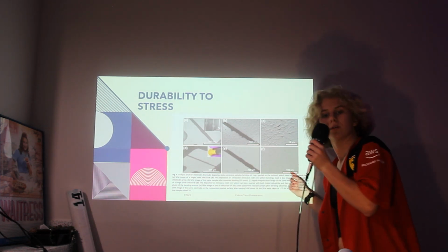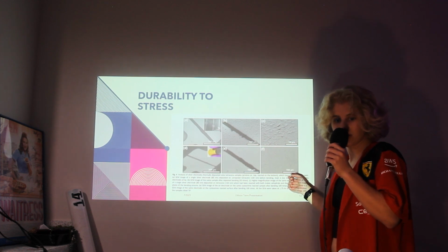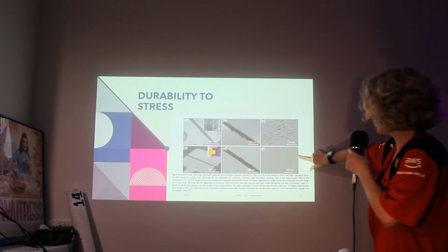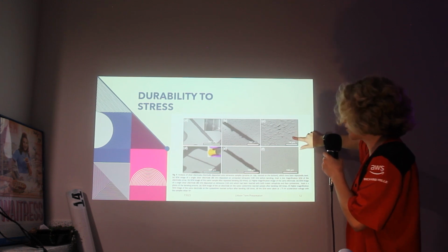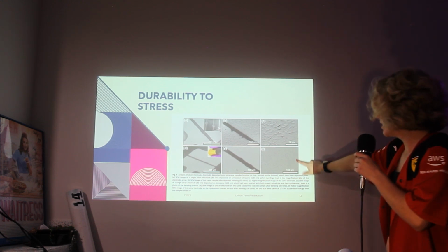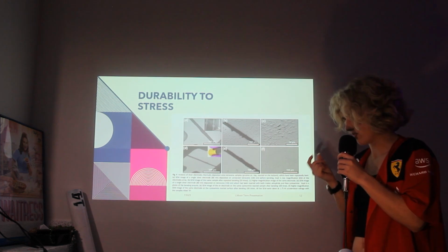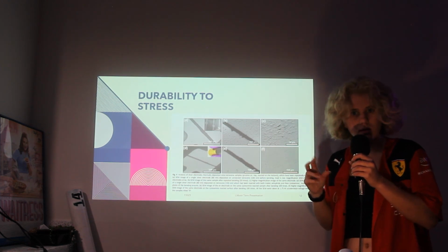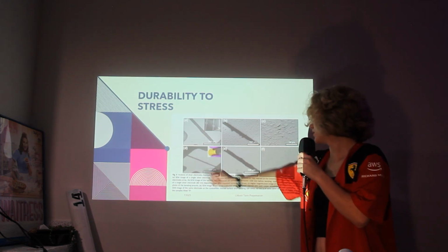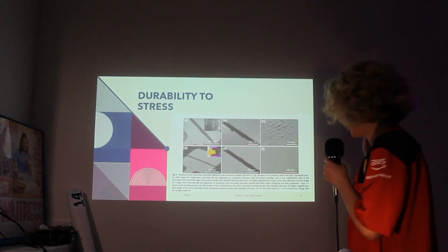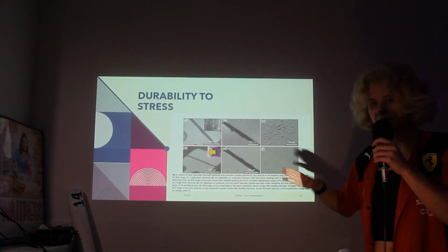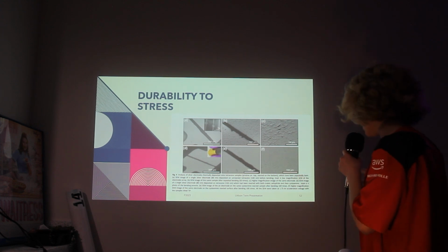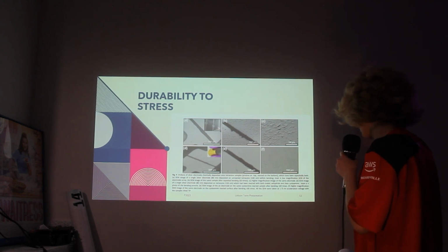In the bottom row of images, they have the treated sample, which, as you can see, even after 100 bending cycles, has none of the flaking, cracking that you can see in the top image. These little dots are seeds of silver that, if the projector wasn't so blurry, you could see in this image as well. So that isn't a new thing. They withstood 100 bending runs.